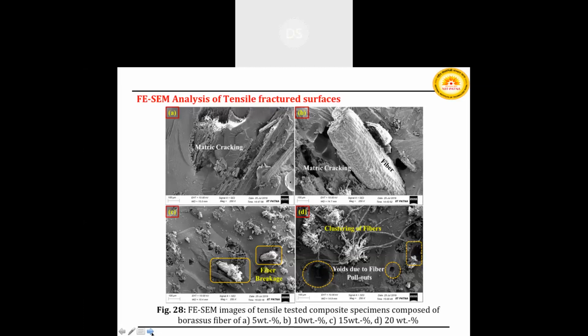In figure 28d, voids are clearly seen due to the fiber pull out because of 20% borassus fiber composite, since fiber is more and resin is less. Because of this poor interfacial adhesion with the matrix, and the clustering of the fiber, the mechanical properties of the composite correspondingly decrease.